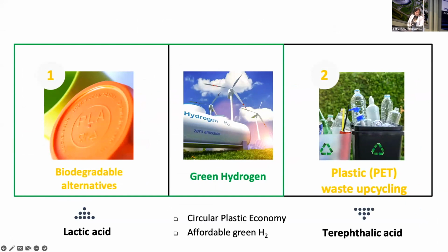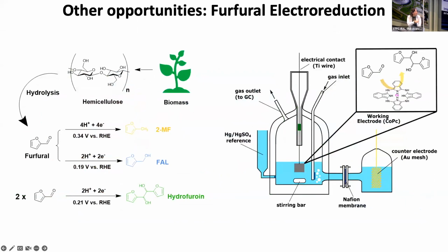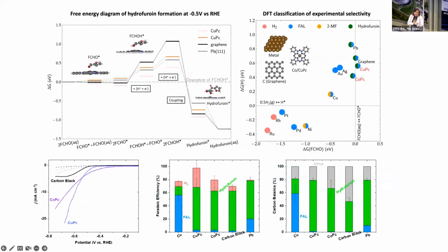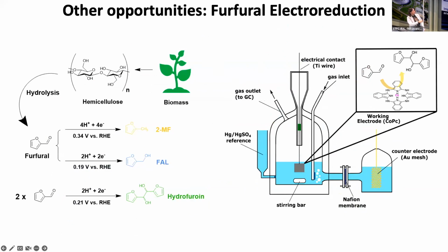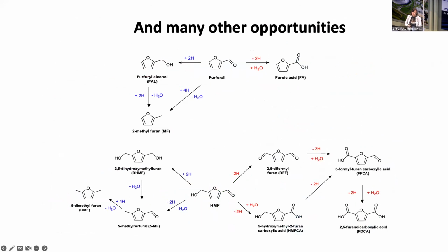We're also doing other biomass reactions, in particular the reduction of furfural to hydrofuroin. That's something we're also doing electrochemically. We're looking at a molecular phthalocyanine catalyst at the moment, supported on graphene or hydrothermal carbons. It seems to be working, and we also have DFT proof that this could work quite nicely. And in principle, if you could open this molecule and hydrogenate it, you could make a jet fuel precursor. And there are many, many other opportunities.